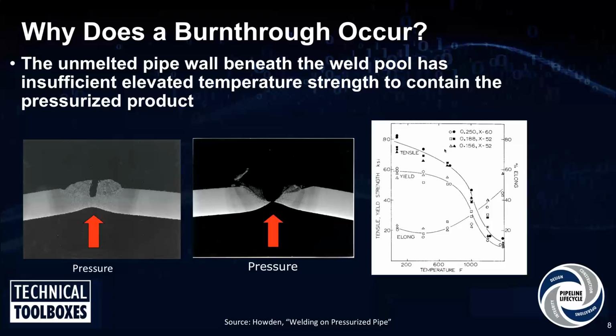Now that same term is used for in-service welding also, but for an in-service welding burn through, the welder doesn't actually blow through the pipe wall. What happens is, as the welder is welding, the area underneath the liquid weld pool is still solid, but it gets really, really hot. When that steel gets hot, steel gets weak. So at some point, that solid piece of steel gets so hot that it loses all its strength, so it just cannot contain the pressure underneath the weld pool. So what happens is the pressure from the pipeline actually blows out, or forces the product out, through the weld pool, through that weak steel.